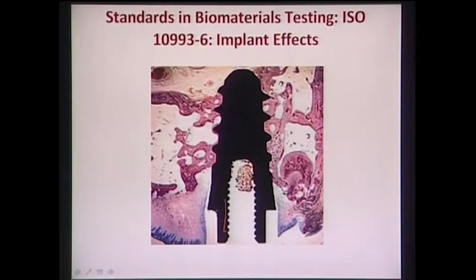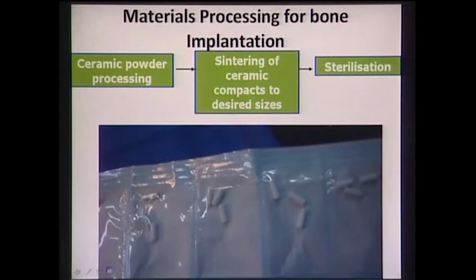This is like dental screws, which are put inside for dental restorative applications. Now, I will show you some of the experiments that we recently carried out. These are the material shapes we typically used in our experiments. As you can see, these are cylindrical specimens, around 2 mm in diameter. So, it is an extremely small size, with an aspect ratio of around 3 to 4. So, 2 millimeter diameter and 8 millimeter length, with a cylindrical cross section; those samples were used in these in vivo experiments.